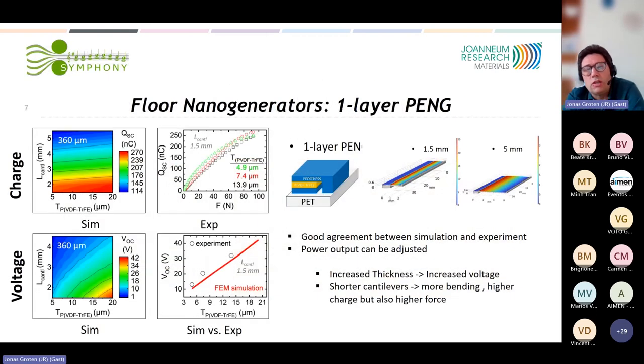Basically, we started here with a simulation to optimize the cantilevers. First, we set up a model for PVDF TrFE to really reflect our output and to compare this with measurement data. Depending on the length of the cantilever, we have, of course, more or less d33 and d31 contributions. So we brought this into a FEM model and simulated with COMSOL different cantilever lengths and thicknesses of the PVDF TrFE layer, and checked that the model is correct.